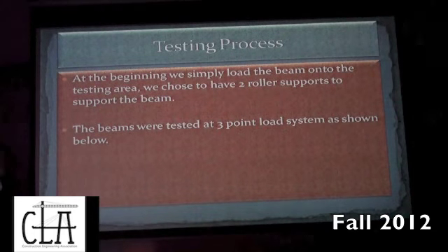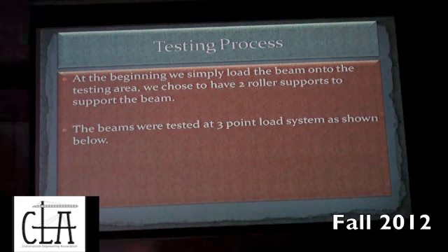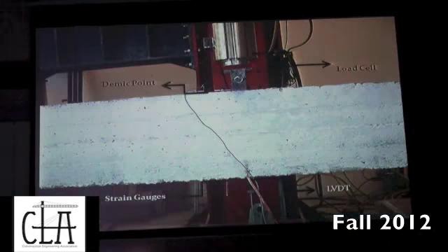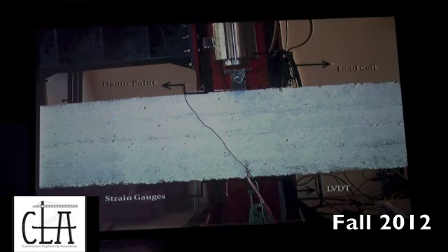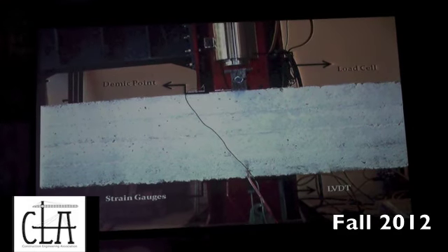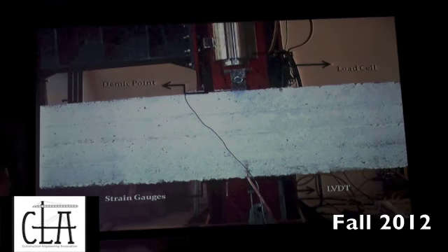In the testing process, at the beginning, we simply load the beam onto the testing area, and we chose to have 2 roller supports to support the beam. The beams were tested with a 3-point load system, as shown below. Continuing the testing process, this is the test setup for every beam we did. We have a demec point on the top of the beam, the load cell, 2 strain gauges, and 1 LVDT.